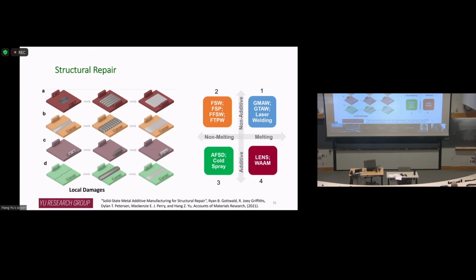So we surveyed different repair technologies and divided them into 4 quadrants, depending on whether melting happens or not, and whether the technology is additive or not. Our conclusion is we want to be in quadrant 3. We want a solid state, non-melting process, but additive. There are two options essentially at this moment. One is additive friction stir deposition, the technology I'm talking about. The other is cold spray. For your background, the Navy has invested a lot of funding in cold spray over the last decade or so. Cold spray has demonstrated great success for surface repair, but for deep holes or deep volumetric damage, additive friction stir deposition is your choice.